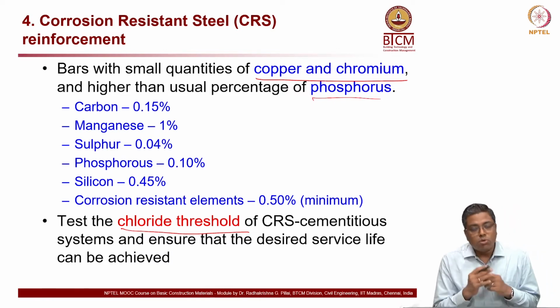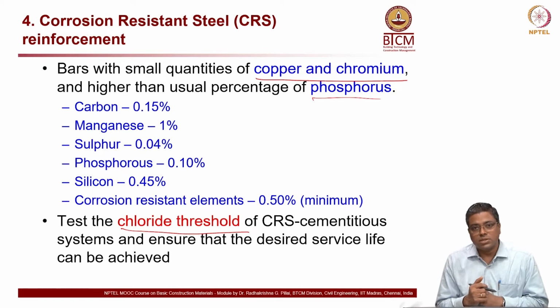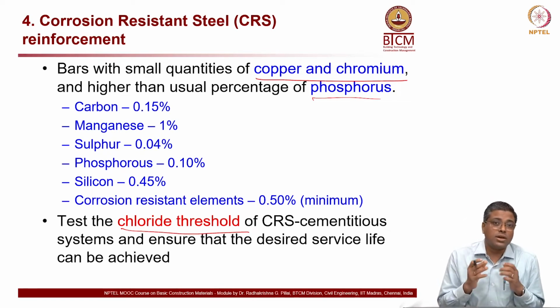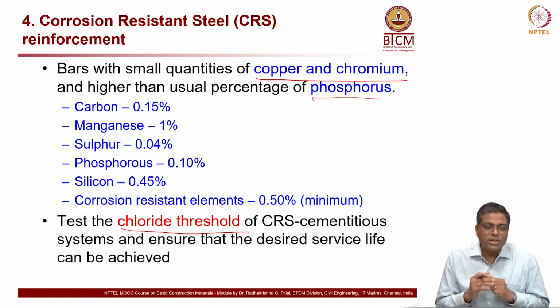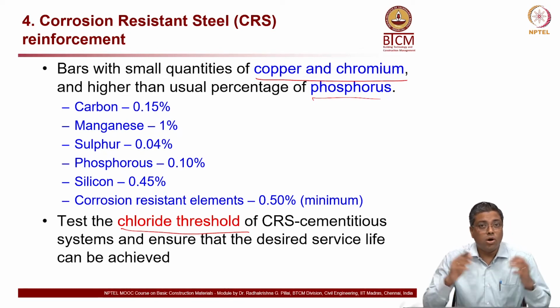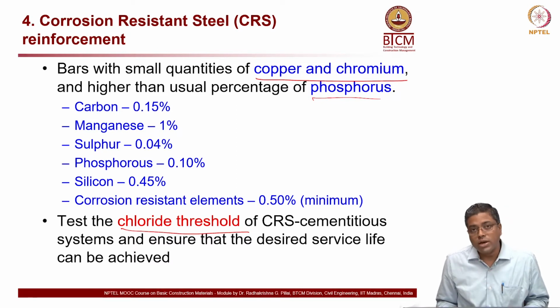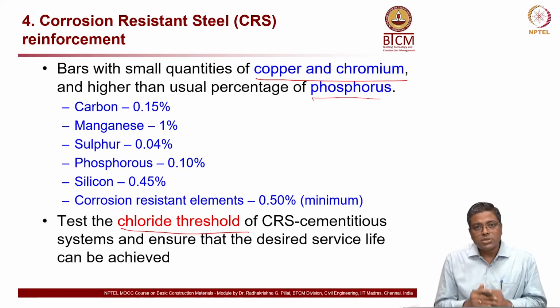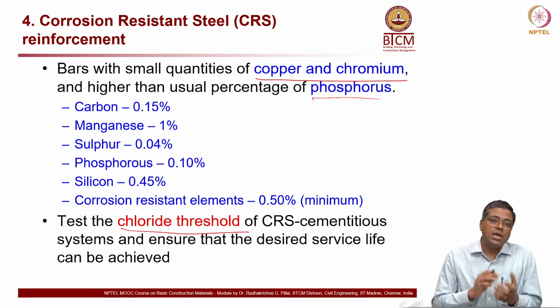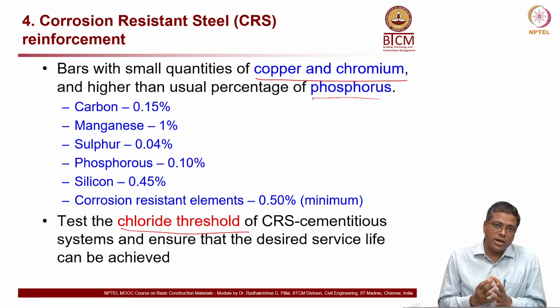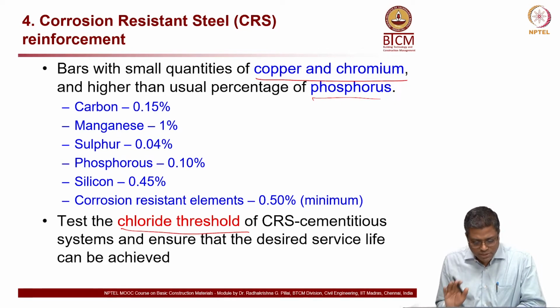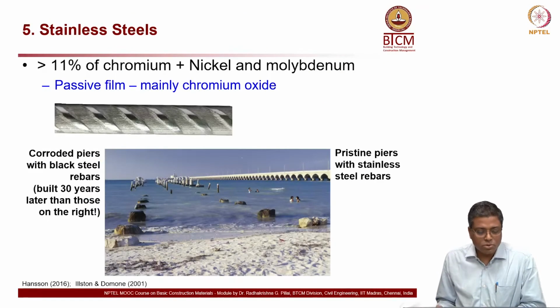Why I am saying this is, most manufacturers, when they sell this corrosion resistant steel, will say that the corrosion rate is low. But that's not the key parameter to look at when we look at long service life of the structures. There is a more important parameter which is chloride threshold, or even pH threshold if you look at carbonation. So chloride threshold is the parameter which you should look at. What is chloride threshold? It is the minimum amount of chloride which is required to cause corrosion. Okay. We'll just leave it at that level. You don't need to go too detailed.